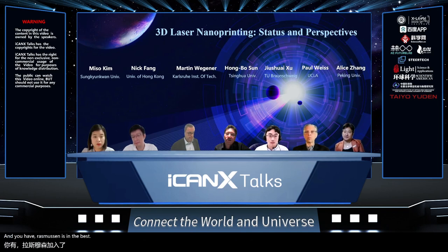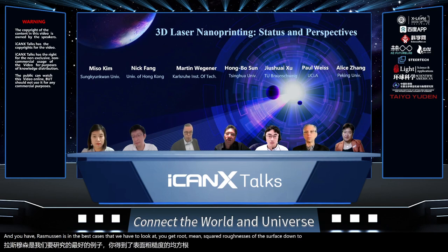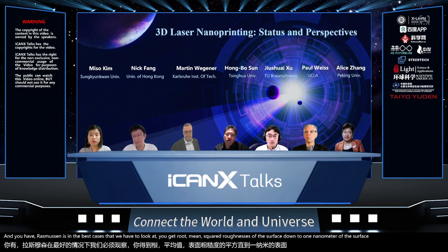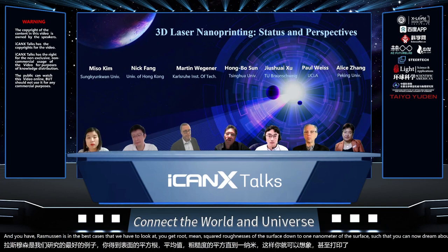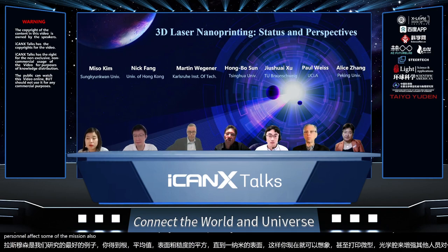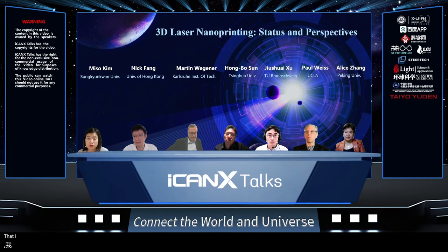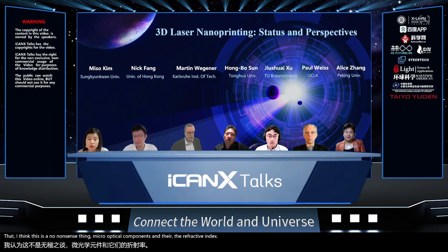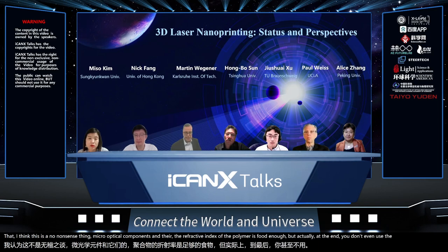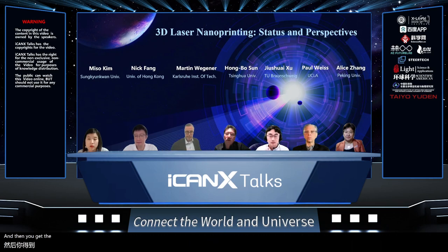On a deep sub-micrometer level, you have roughnesses. In the best cases that we have looked at, you get root mean squared surface roughnesses down to 1 nanometer, such that you can now dream about even printing micro-optical cavities to enhance some emission via the Purcell effect in quantum optics or things like that. I think this is a no-nonsense thing, micro-optical components, and there the refractive index of the polymer is good enough. Actually, at the end, you do not even use the refractive index of the polymer, because you misuse it, so to speak, as a stamp. And then you get the refractive index of the material that you stamp into.